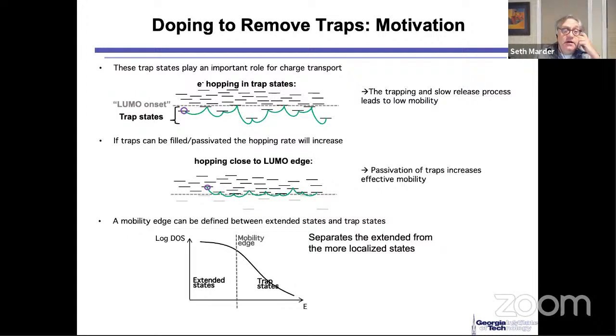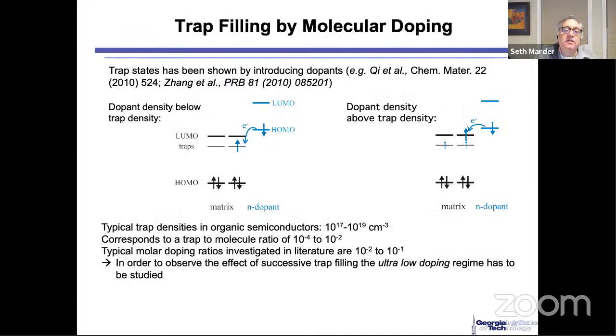Okay, so let's talk about trap filling. As I said yesterday, trap states are important in terms of trying to get high mobility. If you have traps, your electron is going to move slowly. But if you can fill those trap states, then you would think that the energetic barrier for the electron moving will be lower. Using photoelectron spectroscopy and/or inverse photoemission spectroscopy, you can map out the density of states, and this is work that Antoine Kahn is truly expert at. This is a study that we did with Antoine. I think more precisely, this is a study that Antoine did with us.